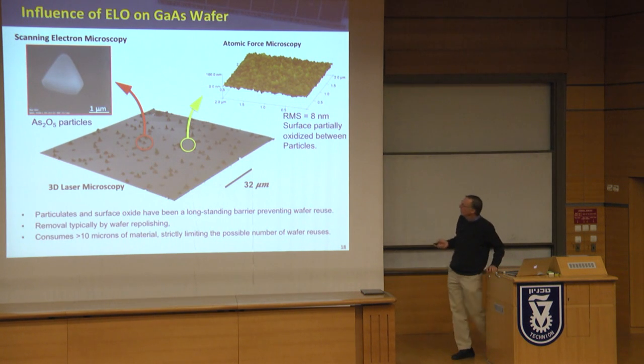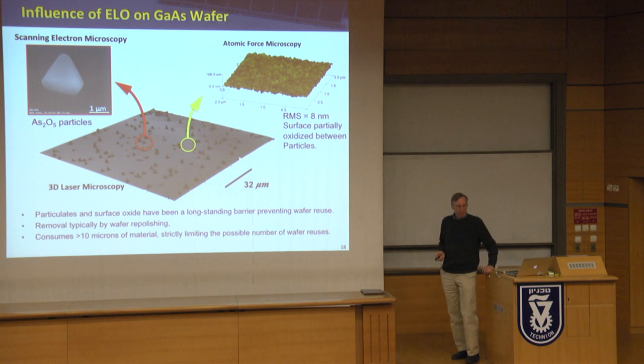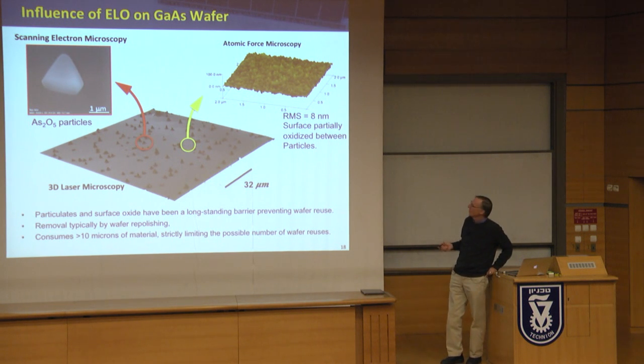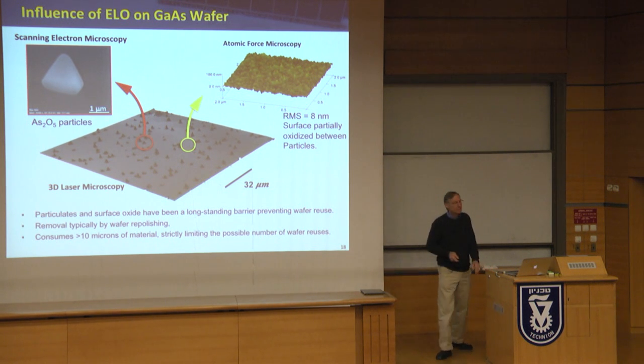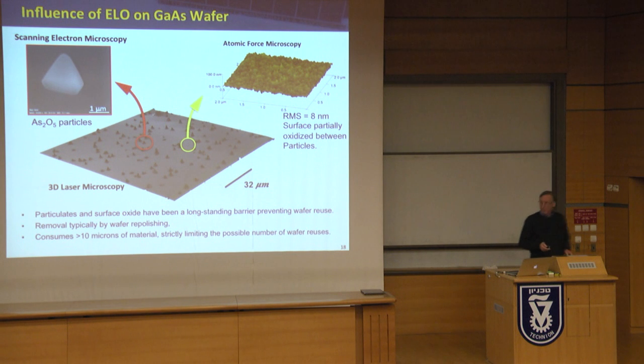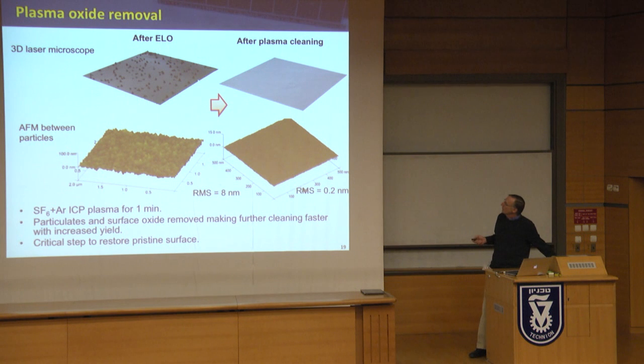Now, as I mentioned, when you do that, you're left with a surface that's loaded with these little stones. This is the wafer surface after you do the epitaxial liftoff, and this is what people have been dealing with for decades. And these little stones are arsenic oxide particles, and those particles are very inert. There's very little that takes them off. So the first thing we do, which preps the surface, so this is the gallium arsenide wafer substrate. The epi is gone. It's sitting on some plastic somewhere else.